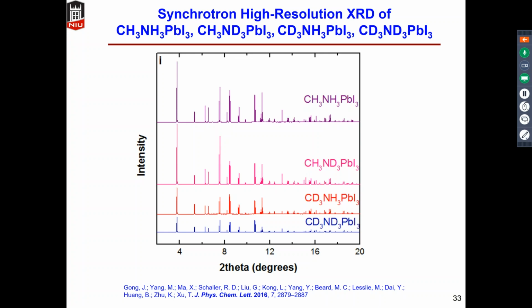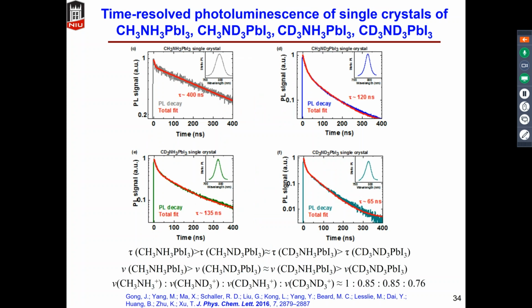effect of these isotopes. We measured the time-resolved photoluminescence, and we found that the pure hydrogen-based perovskite single crystal has the longest carrier lifetime, while the 2 half-deuterated MAPbI3, one nitrogen hydrogen deuterated and one carbon hydrogen deuterated, both show comparable carrier lifetimes. However, when we tested the fully deuterated MAPbI3, its carrier lifetime drops significantly. So the carrier lifetime seems to have a direct link with the mass of these rotors.